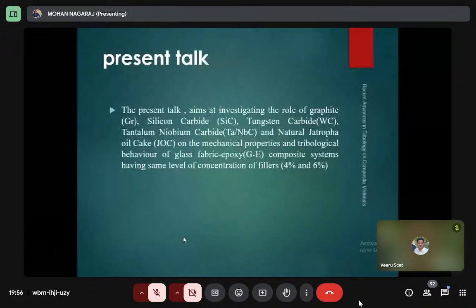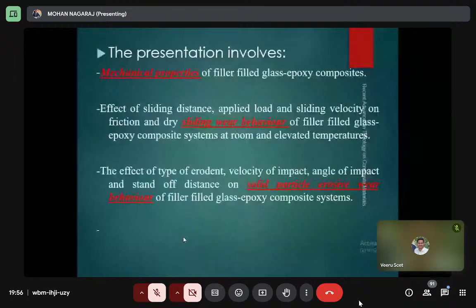Generally, Jatropha is cultivated. After crushing the Jatropha, it is used like diesel in the engine. After obtaining the husk of the Jatropha, those particles are also used in glass epoxy composite materials in different combinations and percentages. It also gives an enhancement in the wear properties. We also studied the mechanical properties, sliding wear behavior, and solid particle erosive wear behavior using filler filled glass epoxy composite.